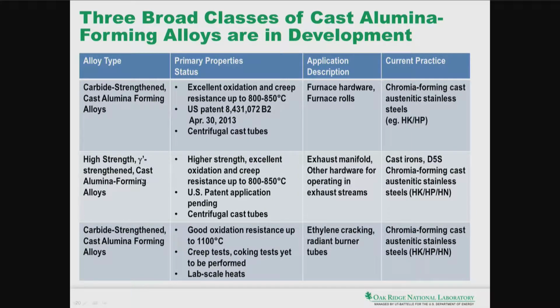And the second class of alloys that we have are relatively higher in strength than the HK and the HP type of alloys. They have much better, much higher strength, and they have a much sharper drop-off in strength above these temperatures. So there's a hard limit as to temperature, maybe about 900 C. It's probably the maximum that you would be able to use these alloys.